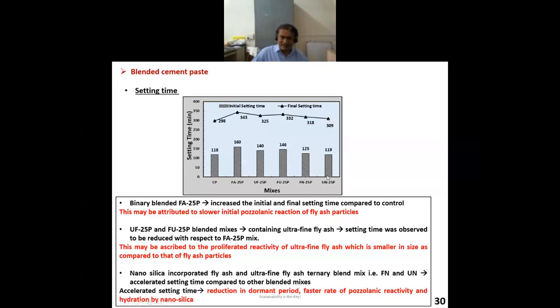But the moment I added nanoparticles, in these last two mixes, the setting time was very similar to the control. We have done some research where we have replaced cement with only nanoparticles. Now remember, these two are combinations of secondary cementitious materials and nanoparticles. The replacement is 25%, written as 25p, so out of 25, 2% is nanoparticles and 23% is secondary cementitious materials.